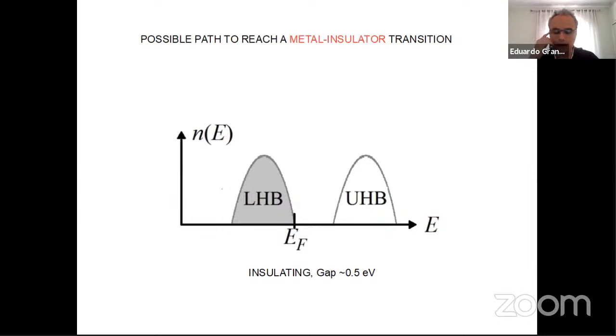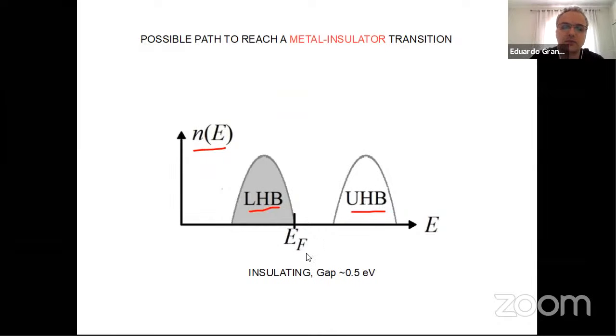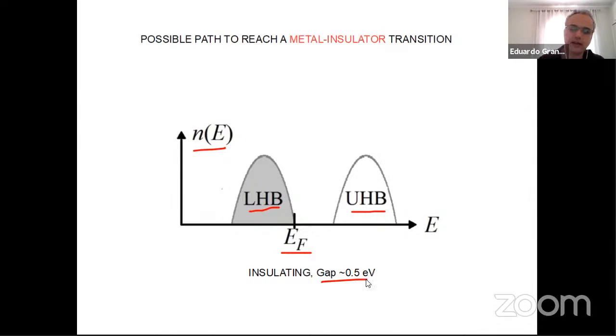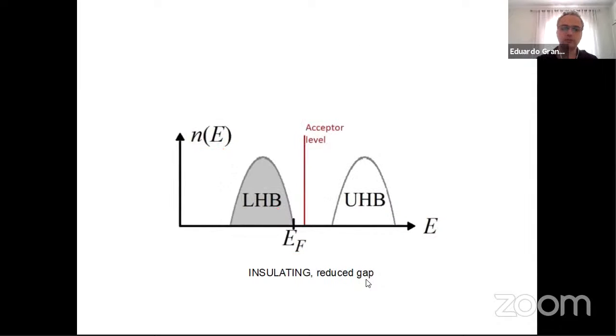So now how do you attack this problem? We propose a different path to reach this metal-insulator transition. Now I have this diagram here again. This is a band diagram. We have the energy versus density of states. So this is pretty much the lower Hubbard band and upper Hubbard band, as I mentioned before. The LHB is fully occupied with electrons. The UHB is empty. So that's why you have an insulating material. And the Fermi energy, which is the energy of the last, the most energetic electron, is indicated here. So in principle, in the pure material, you have this gap of about a half electron volt. Now, instead of applying external pressure, we want to make a chemical substitution.